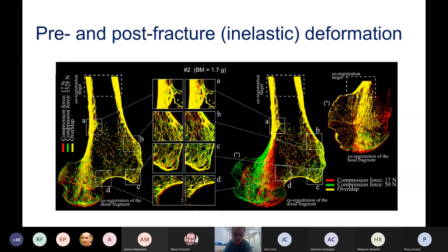And in the middle, you see some area where we are looking in detail at what has been displaced and what is not. It says that there is no evident permanent inelastic deformation of bone, with the exception of some region very close to the fracture region. On the contrary, on the femoral head, on the fracture fragment, we do see a substantial permanent deformation in the head.